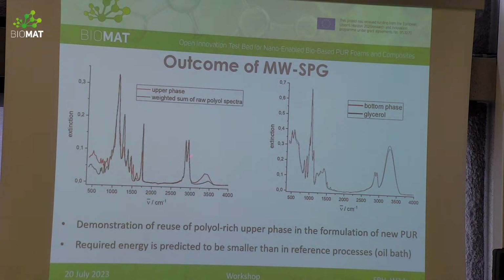But by IR spectroscopy, we could prove, at least for the upper phase, given here in red, that we can compare this spectrum of the upper phase with a weighted sum of the raw polyols used in the original formulation, and this proves that the upper phase is the polyol-rich one. And also for the bottom phase, if we compare the spectra, we see that the bottom phase and the spectrum of glycerol, they fit pretty well one to each other.